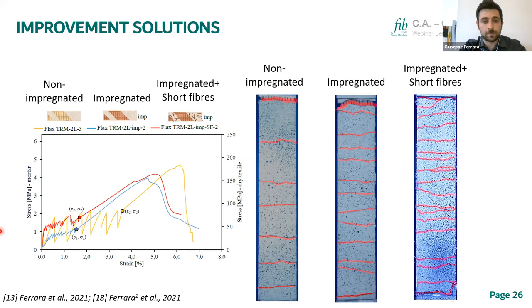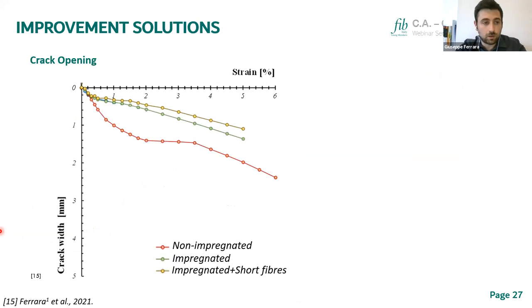of the composite. If we look lastly, for example, at the results in terms of crack openings, it is a very significant aspect in terms of durability, also performance of the system. If we fix our attention on one strain, we can see that non-impregnated textile has some values of crack width. When we use impregnated textile, we significantly reduce the crack openings, and we even have a beneficial effect when we use also